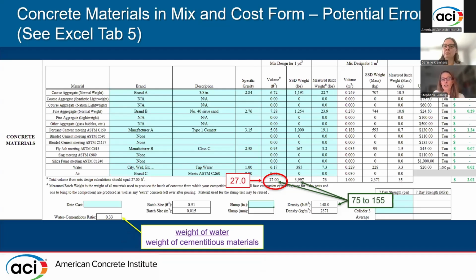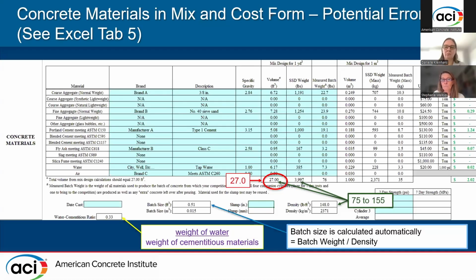The water to cementitious ratio is also calculated for you by the spreadsheet. It is equivalent to the weight of water divided by the weight of all of the cementitious materials, including the blended cements, Portland cement, fly ash, slag, and silica fume. Batch size is calculated automatically and is equal to the batch weight divided by the density.